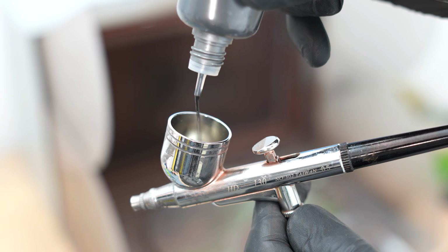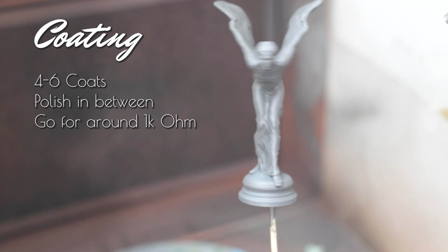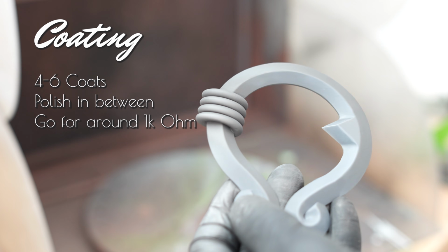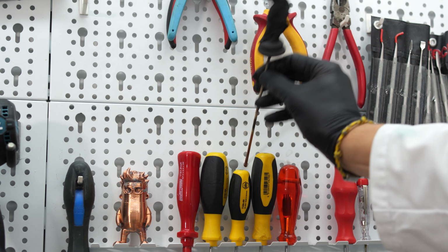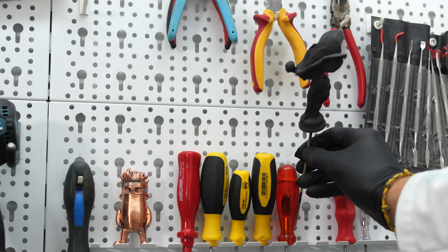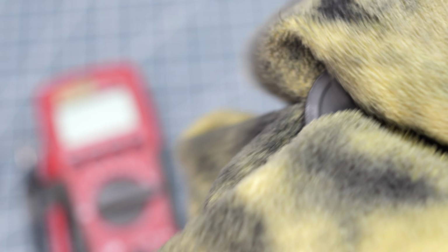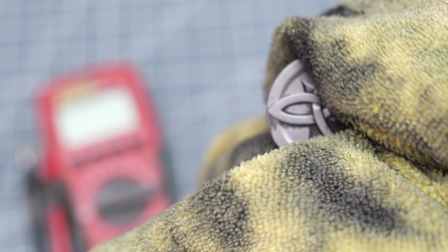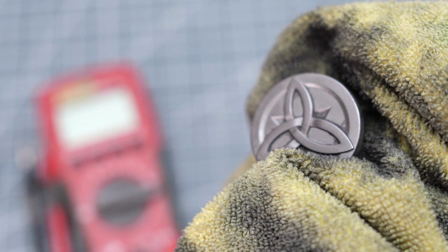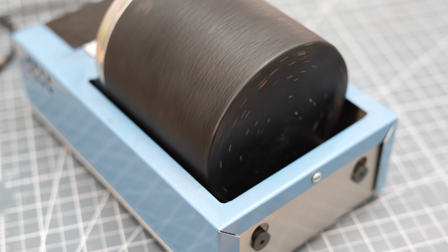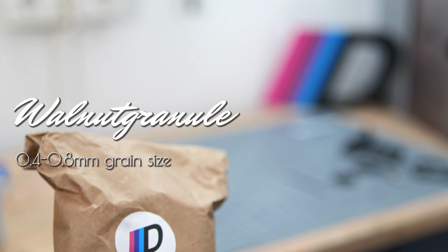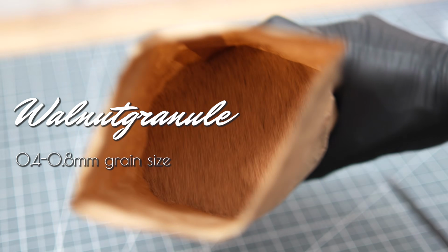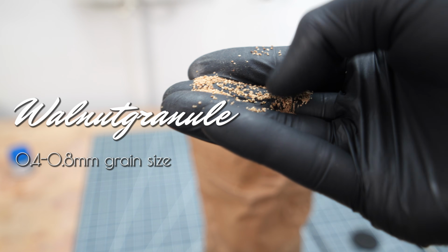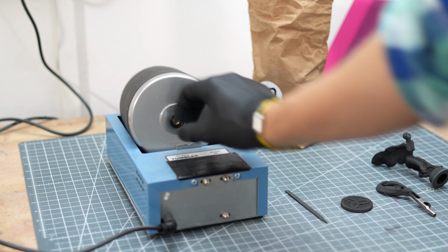Now you can start spraying the parts. I recommend applying at least 5 coats, allowing each layer to dry thoroughly and then polishing with a cloth in between. This will lead to an increasingly better conductivity. This conductivity is essential for ensuring the electrolyte deposits evenly and rapidly. Of course, you can also use a rotary tumbler with walnut granules. In case anyone's curious, it's about 0.4 to 0.8 mm grain.